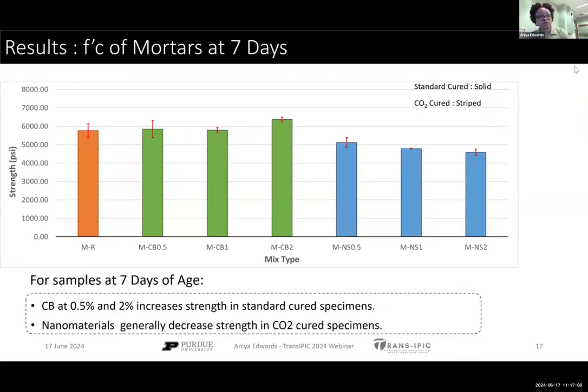However, for the compressive strength of mortars at 7 days, we're seeing something a bit different. Compared to our reference, we're seeing that most of our carbon black samples can slightly increase the strength, except for our carbon black at 1%, which is slightly lower by a negligible amount. But then for our nanosilica samples, we're seeing an apparent decrease in strength, which is surprising because in most nanosilica studies, we actually see an increase in strength, but this might be because of our curing conditions.